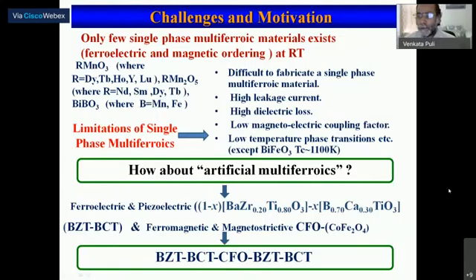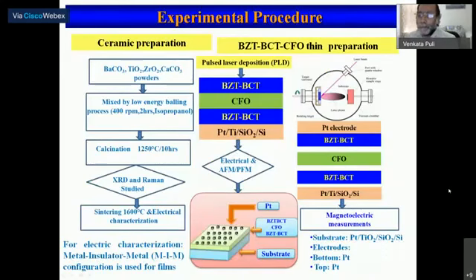Here we have combined the ferroelectric and ferromagnetic phases. The ferroelectric phase is barium zirconium titanate and barium calcium titanate, a solid solution. We took magnetostrictive and ferromagnetic CFO, which has the inverse spinel structure, whereas the ferroelectric phase has the perovskite structure. We made the sandwich structure using the pulsed laser deposition technique on a platinum silicon substrate. We took ceramic targets of both ferroelectric and ferromagnetic phases and made the thin film depositions using PLD. We also made all the structural and morphological characterizations. For electrical measurements, we used a metal insulator metal configuration, with the bottom electrode as platinum, the substrate itself, and the insulating materials sandwiched as ferroelectric, ferromagnetic, ferroelectric. That's why we call them tri-layers.